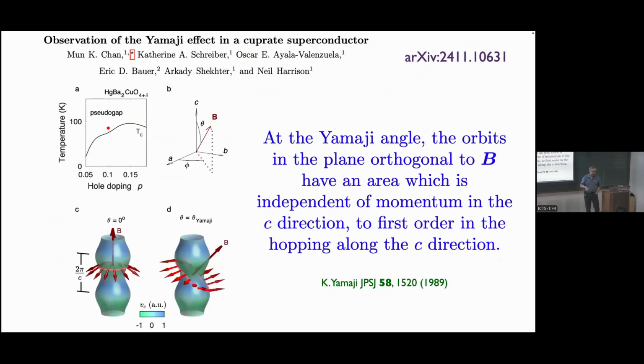Okay, and then very recently there's been this amazing experiment which has gotten us quite excited. It's something called the Yamaji angle. It's also measuring angle-dependent magnetoresistance, but now in a different material. This is the mercury material, above TC, right in the pseudogap, at doping of 0.1. And there, they see something called the Yamaji effect.